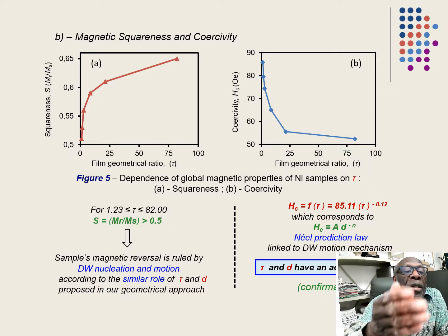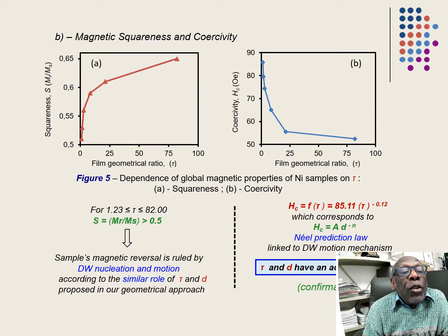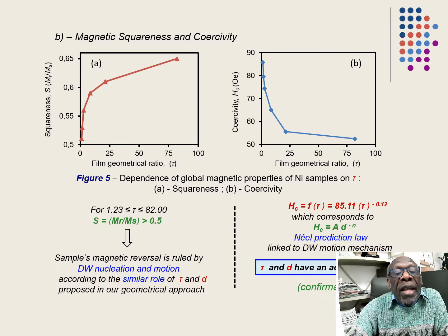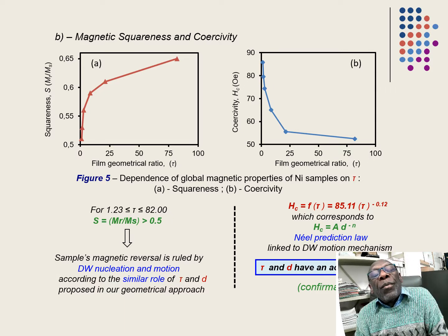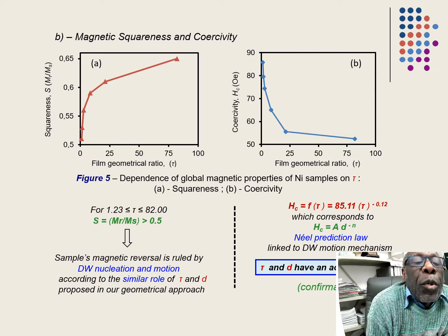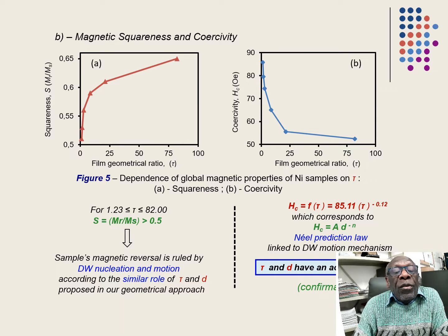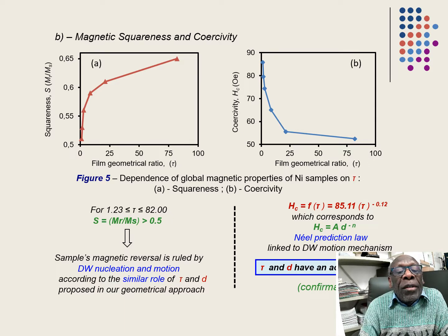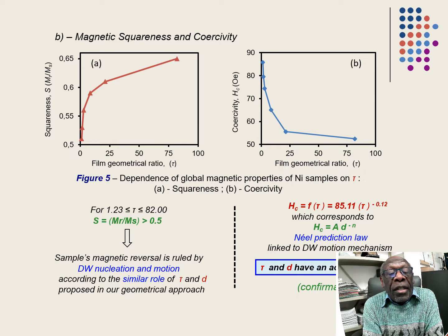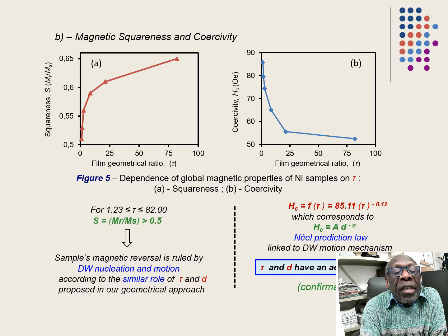Okay, let's see the evolution of coercivity. The expression in red here corresponds to the result obtained, the profile of the curve, and we can observe that the profile of the curve is very close, respects the Néel prediction law when we use d instead of tau. This is the first confirmation that tau and d are similar in their role.